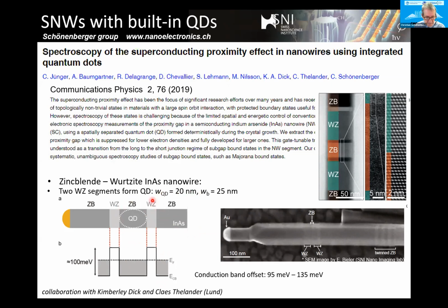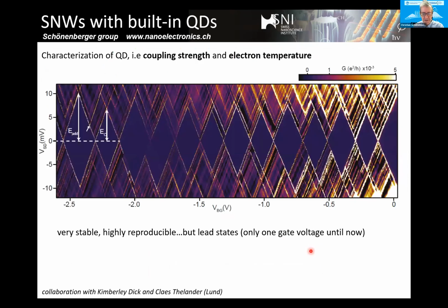So this object is longer than what you have seen before. It's maybe 50, 60 nanometer long. It's also hard to see because it's the same material in a normal electron microscope, just the orientation, that's just the order of the atoms changed in the crystal. So these are even better quantum dots, as you can see here. This is a measurement where you see Coulomb blockade diamonds with normal metal contacts and large addition energies on millivolt scale, charging energy also 5 millivolt or so, and very, very stable, no switches.